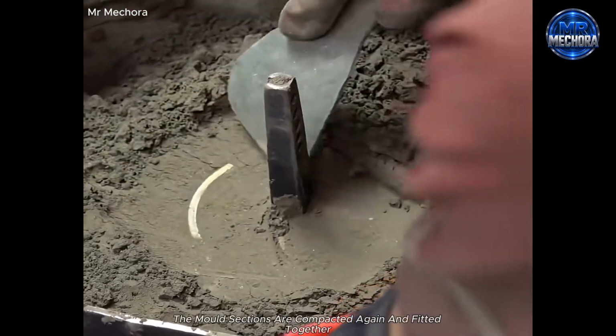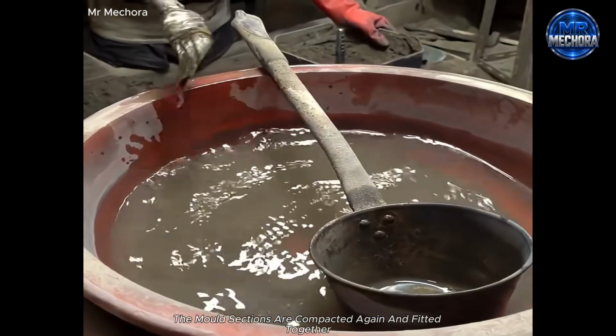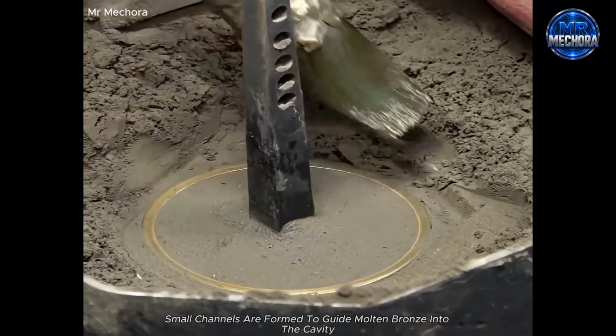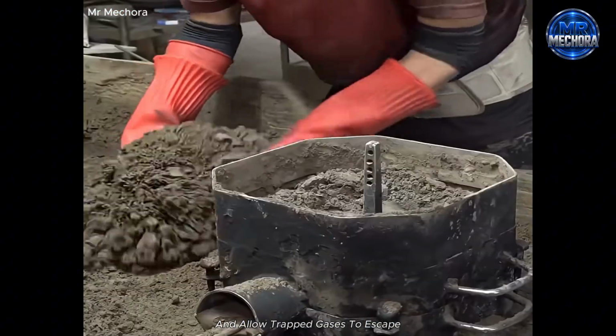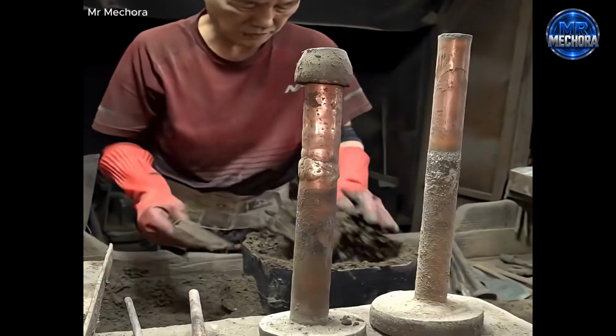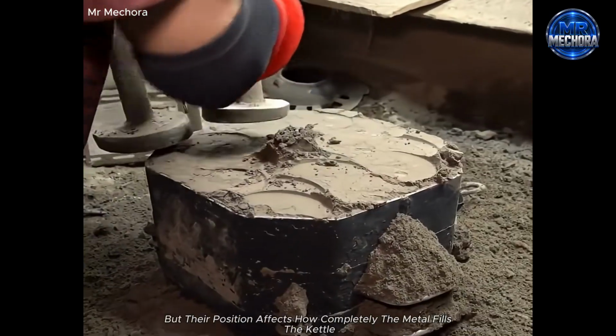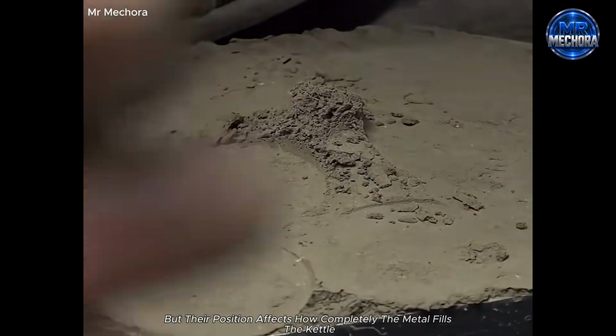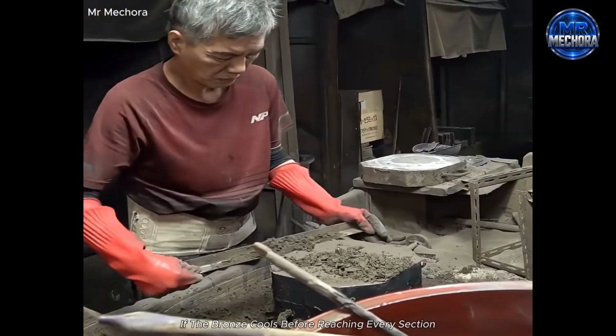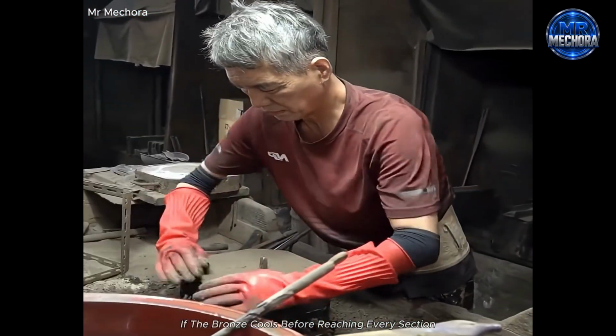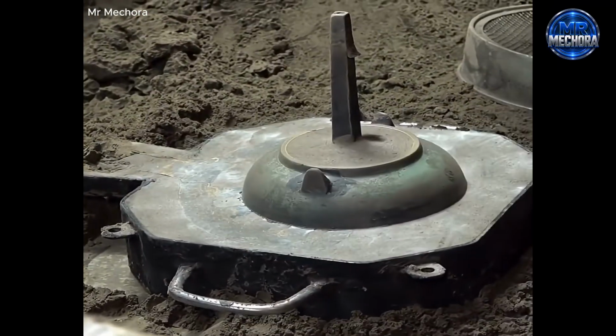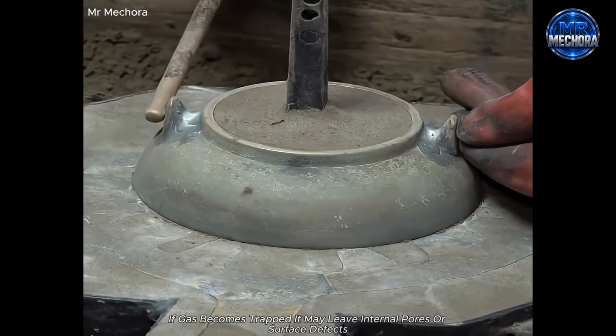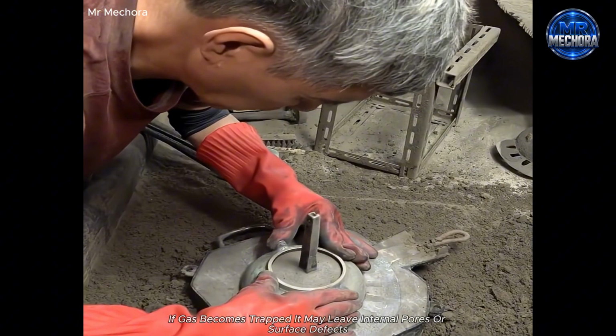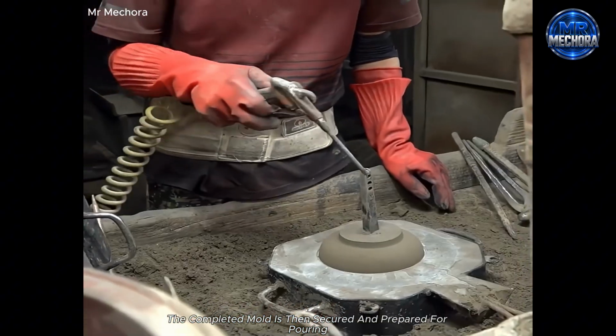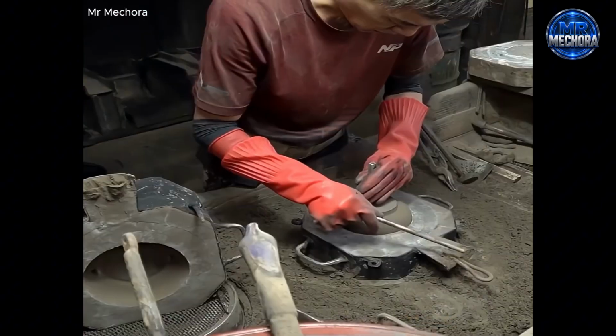The mold sections are compacted again and fitted together. Small channels are formed to guide molten bronze into the cavity and allow trapped gases to escape. These passages may look simple, but their position affects how completely the metal fills the kettle. If the bronze cools before reaching every section, the casting can be incomplete. If gas becomes trapped, it may leave internal pores or surface defects. The completed mold is then secured and prepared for pouring.